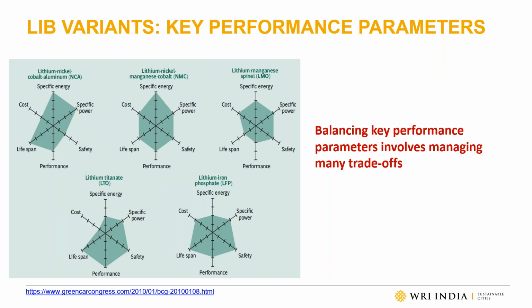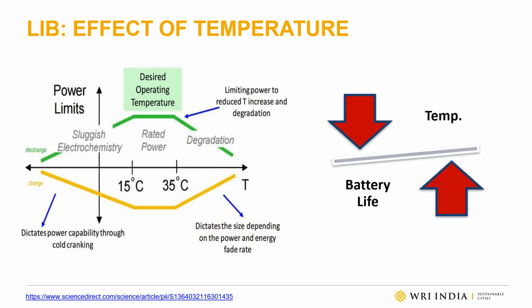As I mentioned, one can use LFP with the graphite anode. This can offer relatively better safety, but one needs to compromise on the other performance parameters. NMC with LTO can offer long cycle life and stability at high charge discharge rate, but high cost and weight of the battery will become an issue. In short, each option comes with some pros and cons. One can choose lithium-ion variants as per requirement.